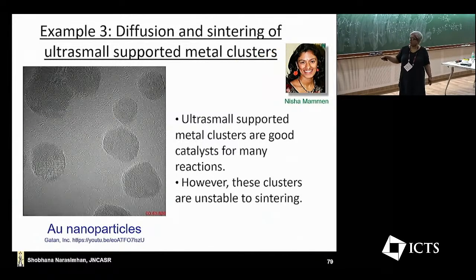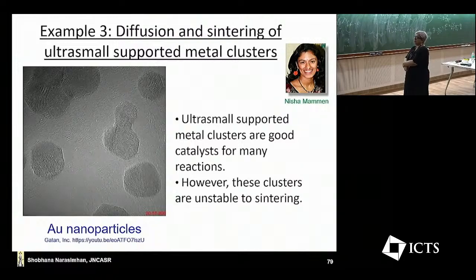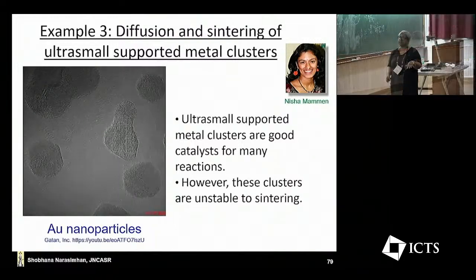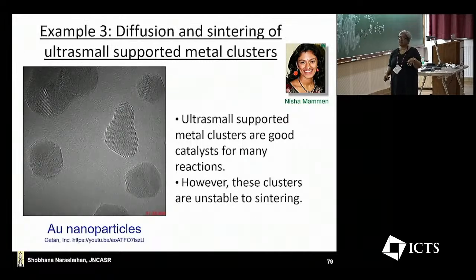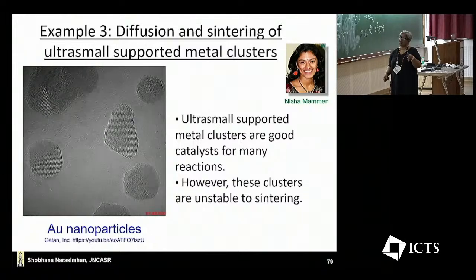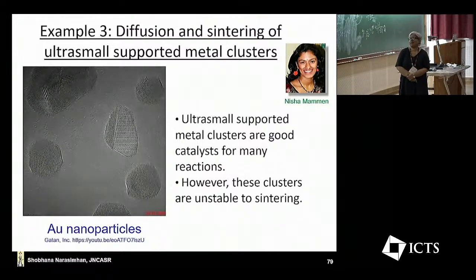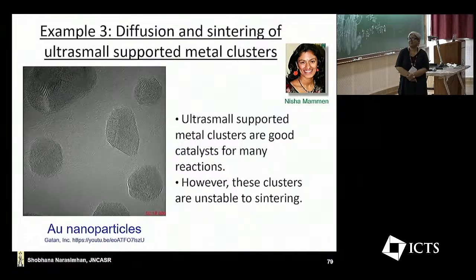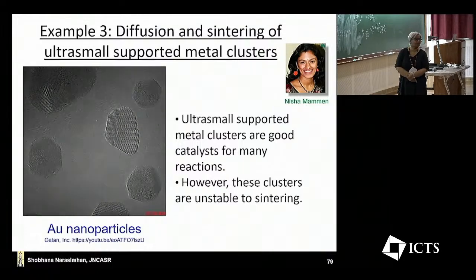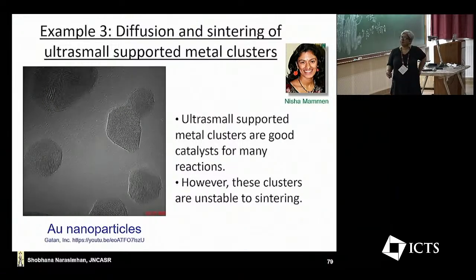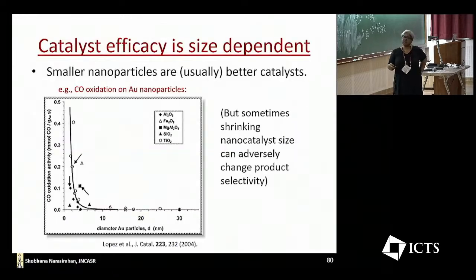this is an electron micrograph. This again shows gold nanoparticles on an oxide substrate. Now if you watch when I run the video, you'll see these two gold nanoparticles join up to form another larger one, and these two do too. So can you see the video? You saw those two join? So they move along the surface, that's called diffusion, and then they join up, which is called sintering. If you wait long enough, you will see, I don't know if I'll wait that long, let's see a bit. You can see at least they're approaching each other. By the way, every little dot on that is an individual gold atom. Okay, happened. Okay, now this is something we don't want.